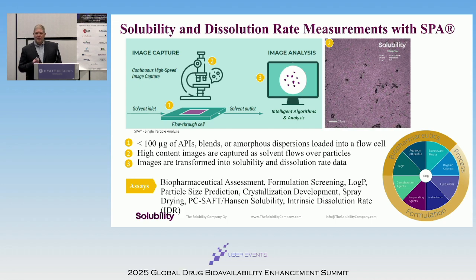So with the solubility company, they're a small startup out of Helsinki, Finland. I went over there for 3 weeks, learned their technology, built a lab, and then brought it back to the United States. And it's been running for about almost a year and a half now. Essentially, you need a tiny quantity of API to measure solubility. We're talking about less than 100 micrograms, so it's basically preparing a slide for a microscope. If you could see too much of it, you probably have too much sample loading. So very small. And it just has to be a powder.